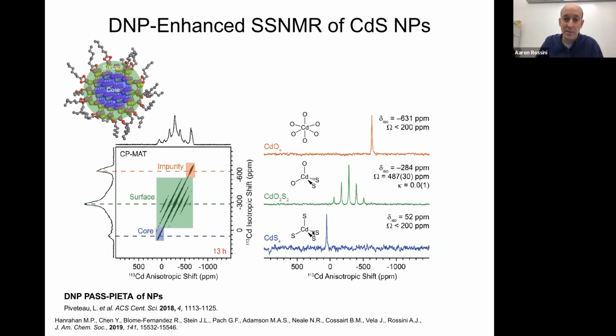As we would expect, cadmium sulfide has negligible or 0 CSA because we have a symmetric cadmium atom. It's tetrahedrally coordinated by 4 sulfur atoms. The surface atoms, though, have 2 oxygens and 2 sulfurs. That breaks the symmetry of our tetrahedron and leads to an appreciable CSA. And then this impurity, we think, is octahedrally coordinated cadmium and also has negligible CSA.